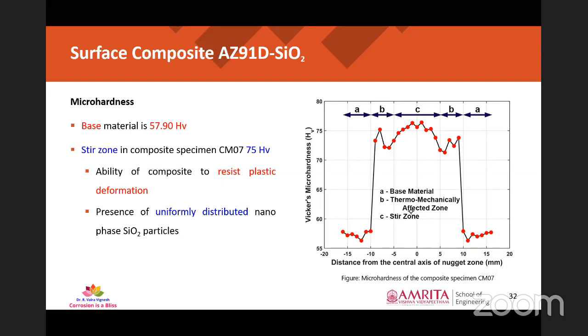Coming towards the composite hardness. The base material hardness was around 57.9 Hv, but in the case of the composite, in the stir zone, the composite had an average micro hardness of 75 Hv. So this attests the ability of the composite to resist plastic deformation, and this is attributed to the presence of nanophase silica particles that act as barriers towards dislocation motion. That is why we have got better hardness in the stir zone of the material. And in the thermomechanically affected zone, because of the presence of elongated grains along a certain direction, there was a minor drop in microhardness values too.